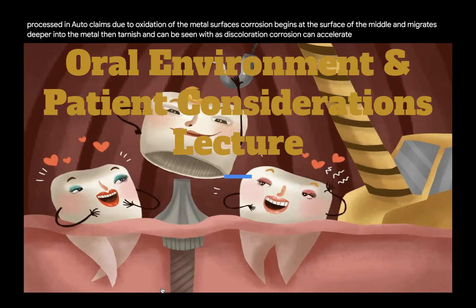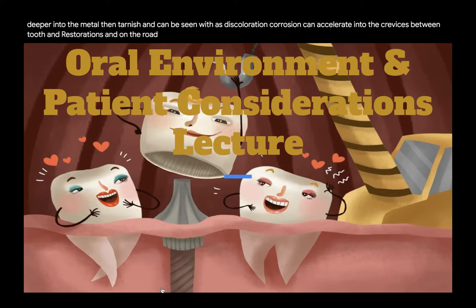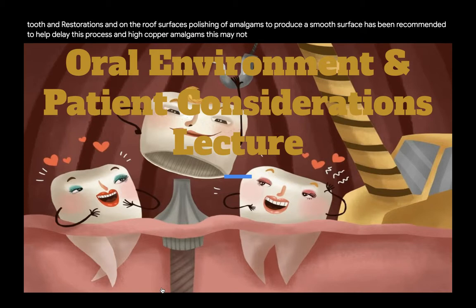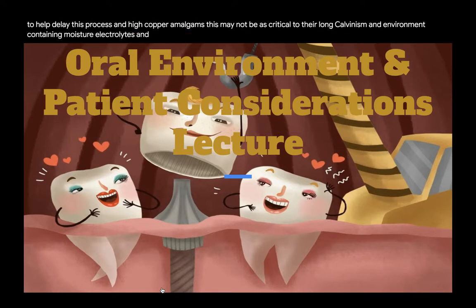Corrosion can accelerate into the crevices between tooth and restorations and on the rough surfaces. Polishing of amalgams to produce a smooth surface has been recommended to help delay this process. In high copper amalgams, this may not be as critical to their longevity since they are more corrosion resistant than low copper amalgams.